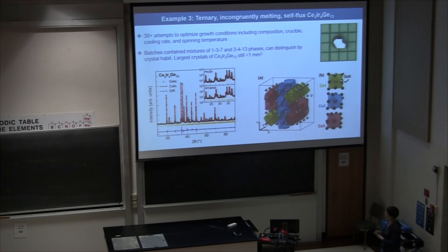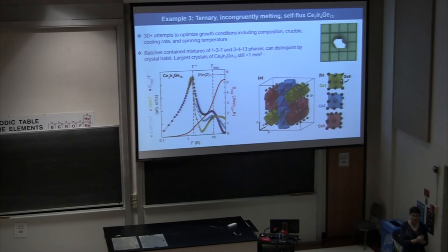So this is the crystal structure where now we have these three inequivalent cerium sites. And the importance of that for our paper was it turns out that in this structure we have a true mixed valence material. Two of our cerium sites are cerium 3+, and the third is a cerium 4+, which is non-magnetic. And so in our property measurements, we only see, for example, an effective moment in susceptibility or an entropy release that is equivalent to 2/3 of the cerium being magnetic. And this completely perplexed us for months until we understood from Julia that we had this reduced symmetry and that only 2/3 of our cerium are magnetic.